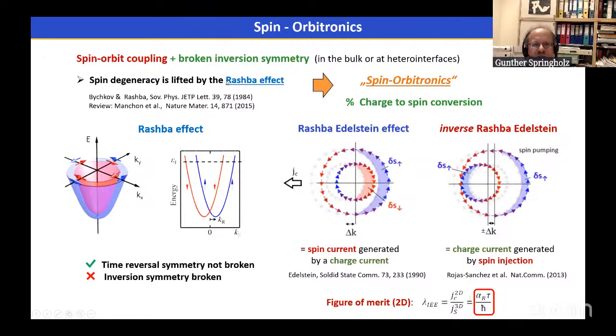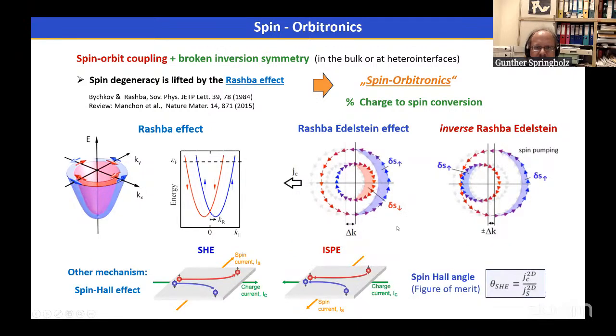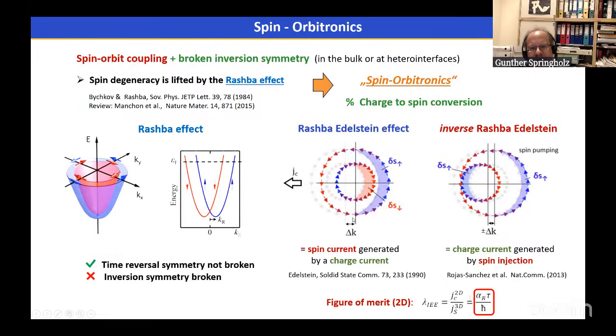Now, how can we use the Rashba effect to do spin orbitronics? The goal here is to be able to convert charge current into a spin current and vice versa. And one way to do this is based on the Rashba-Edelstein effect or the inverse Rashba-Edelstein effect. And that is illustrated here in the middle. So if we apply an electric field, we slightly move the bands in momentum by delta k in the direction of the electric field.